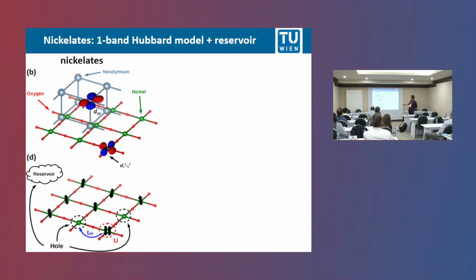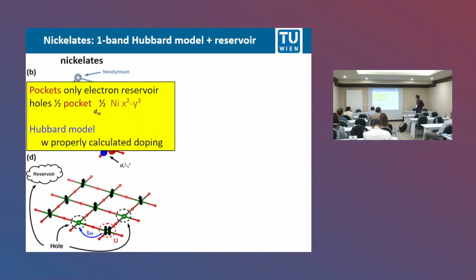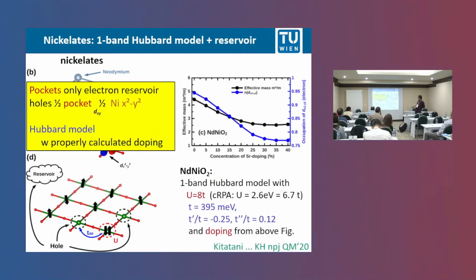And now part of the holes will go here, and part of the holes will go there. And therefore, one has to carefully consider how many holes are going into this x squared minus y squared orbital or Hubbard band, and how many go to this decoupled xy orbital or A pocket. We have calculated this fraction that's shown here. On the right-hand side, for the blue curve, you see the occupation of this x squared minus y squared orbital. And here you see the strontium doping, here for neodymium nickel O2.